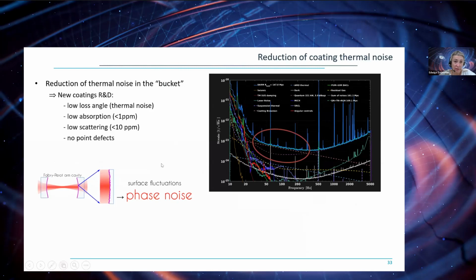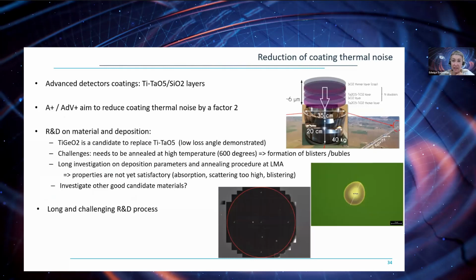So as I said, the coating is the main limitation in the thermal noise that we have in the 100 Hz region. There is a quite challenging R&D ongoing to reduce this thermal noise. Not only do you have to reduce the so-called loss angle of the coating to reduce the thermal noise, but also you have to make sure that this coating has low absorption, low scattering, and no point defect. So this is pretty challenging.